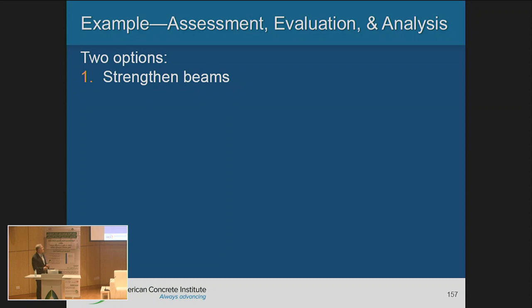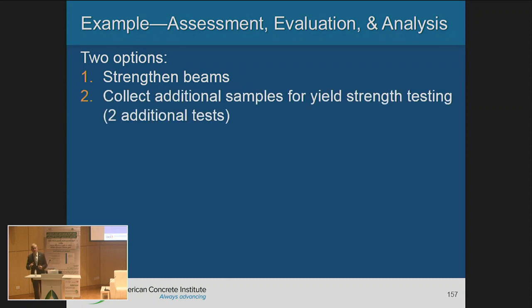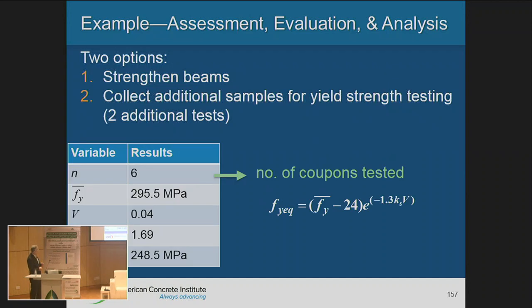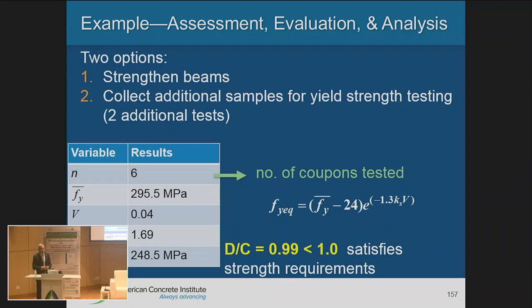Okay? But because it is very close to 1, the engineer said, if I use more test data, I might improve my probability. As you remember, we have that K sub S or K sub C. With the increase in samples, it will decrease, and it will give me a higher equivalent number. If you remember, for the steel, for 4 samples, it was 2.3, I believe. Now he said, I'll take 2 more, taking 6. So that K sub S dropped to 1.7. And the equivalent yield strength increased from 230 to 248. So doing my demand capacity ratio, it's less than 1. And I don't need to do any reinforcement anymore.